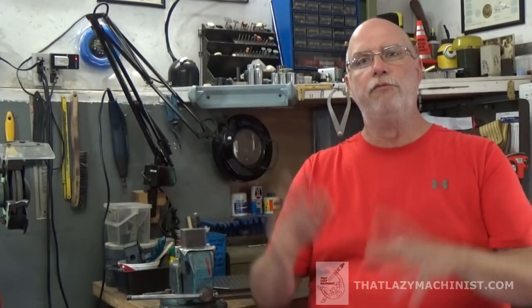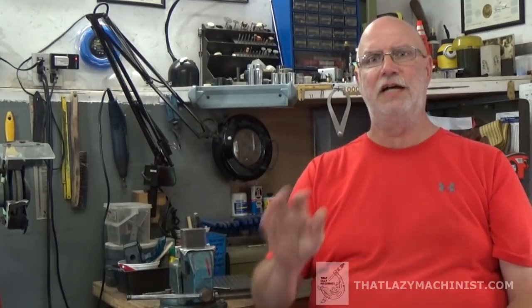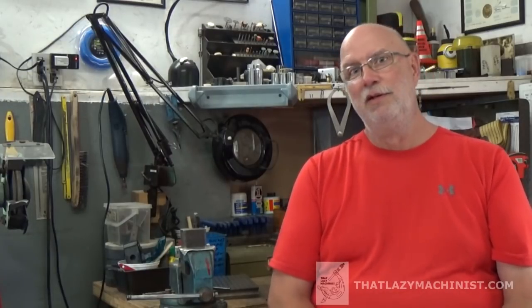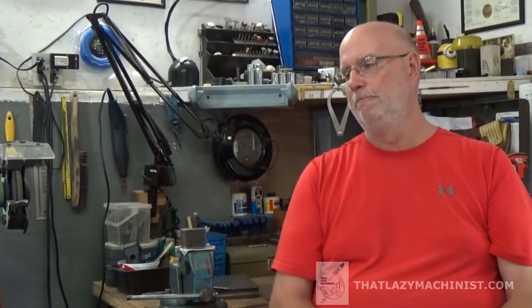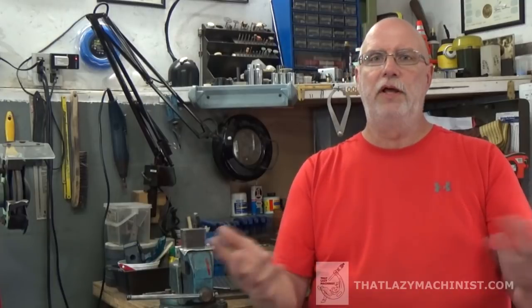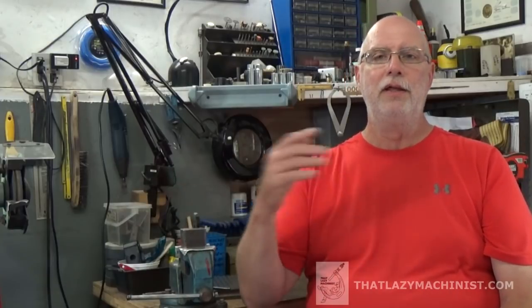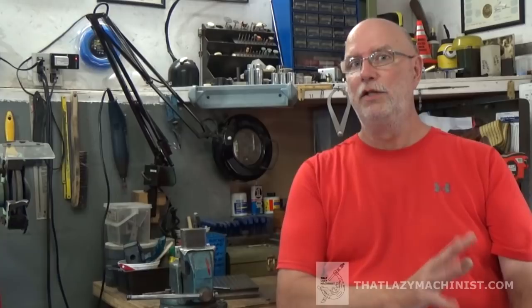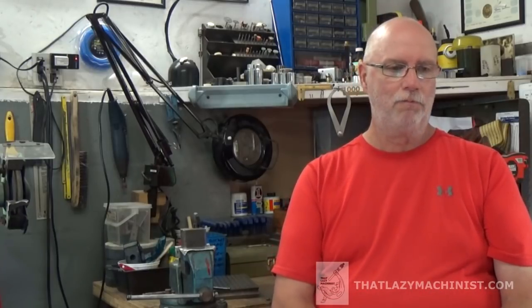Now, once we've reached a certain temperature, it doesn't have to be completely cold, but anywhere under really about 1100 degrees, but we'll play it safe and say 800 degrees Fahrenheit. After that, you don't have to cool it anymore. It's hard or it's soft, but if it did harden, it's going to stay that way. Even if the part is quite hot, it's not hot enough to change that state.